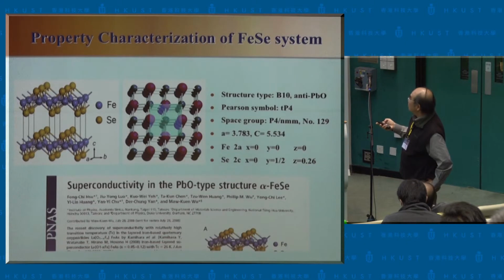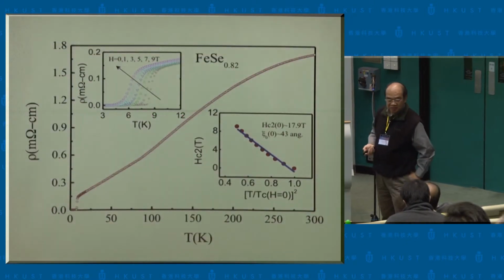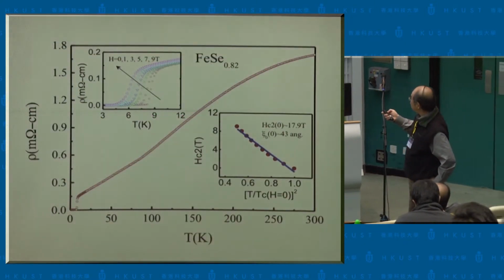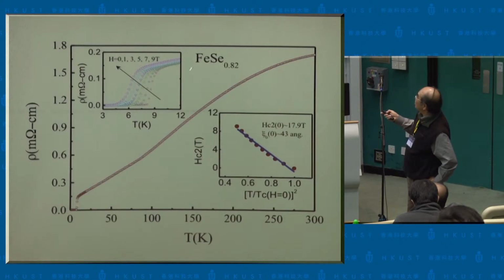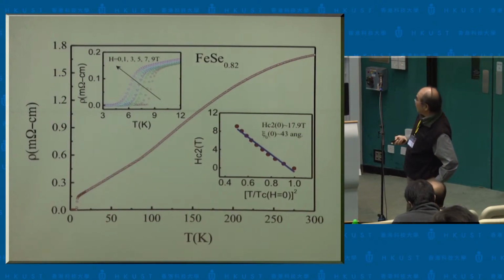The first one, of course, is typically the resistivity. As I mentioned already, there are several features. One is a very high temperature broad bump here. And there's a small dip, and of course, the superconductor transition. And as mentioned, there is some feature around 40 Kelvin, not shown clearly here. But if you use a differential, you can really see that. And what are those features?